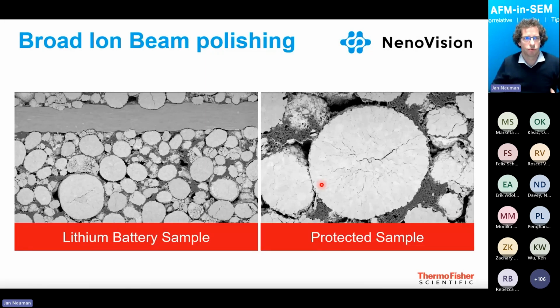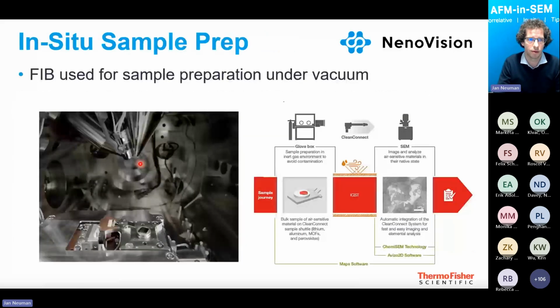The advantage of using broad ion beam is that you can prepare relatively large areas and large cross sections where you have many active materials, in this case cathodes, and then you can choose which one you would like to analyze further. Another approach is in situ sample preparation, which means we are using the focus ion beam directly inside the SEM to prepare the cross-section and the sample.